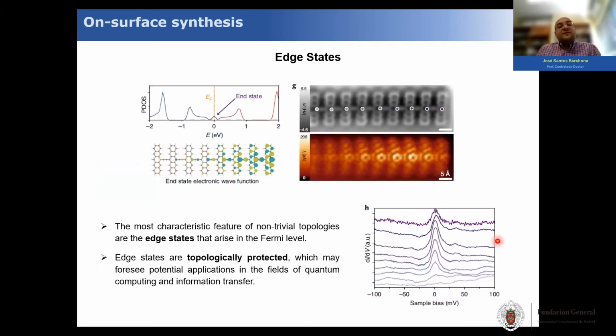Well, another interesting feature of these non-trivial electronic structures is the appearance of what are called edge states. These edge states are characterized by appearing in the middle of the Fermi band here at zero bias, and they always appear at the edges of the molecule, not in the bulk of the molecule. So when you go to the very end of the molecule, what you see is the appearance of these states, which are shown here, both in the STM and also in this plot here.